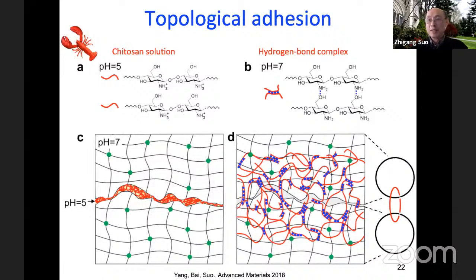But Jia had the wisdom to turn this into a technology, or at least a demo of this topological adhesion. This is his idea. He prepared two pieces of wet material, in his case just two pieces of very stretchable hydrogel, at pH equals 7. And he prepared this chitosan solution at pH equal to 5 and spread this solution on the interface. It's a liquid, you can spread it on the interface, right? And then pH 7, pH 5, pH is just a hydrogen concentration, so it will diffuse. Once hydrogen diffuses into this place, you become what's called a hydrogen bond complex. You make a crosslink. That's all, right? You create this red network. The network connects these two pre-existing hydrogels, right? So that's the concept. It really worked.